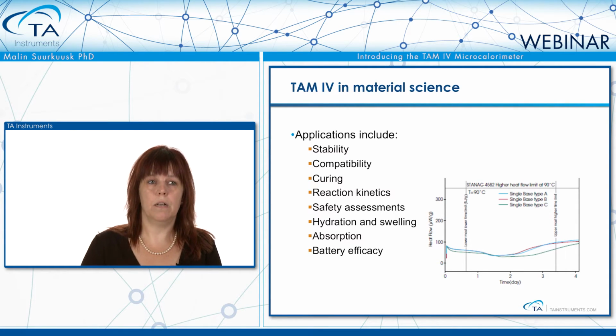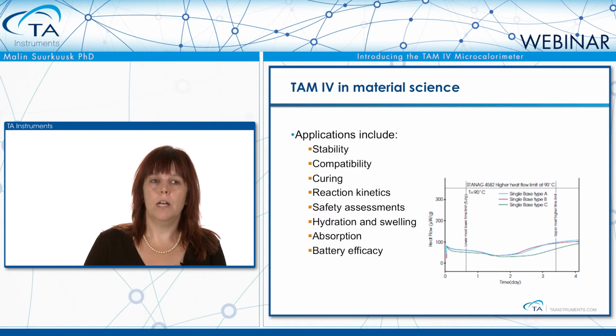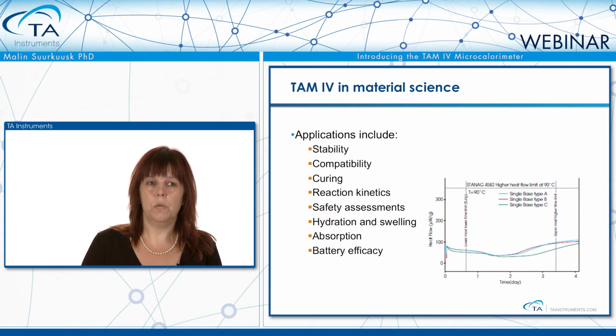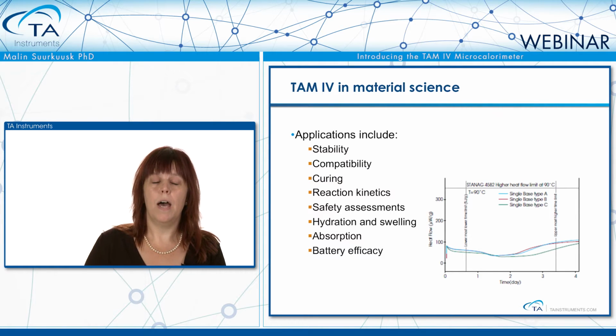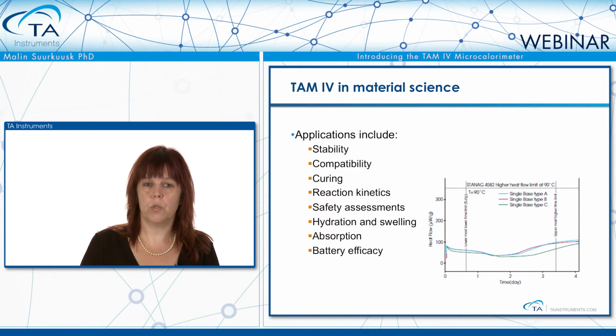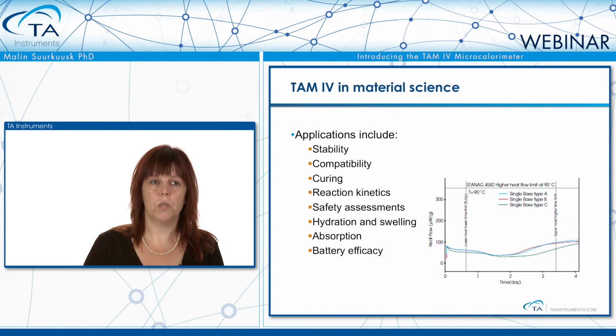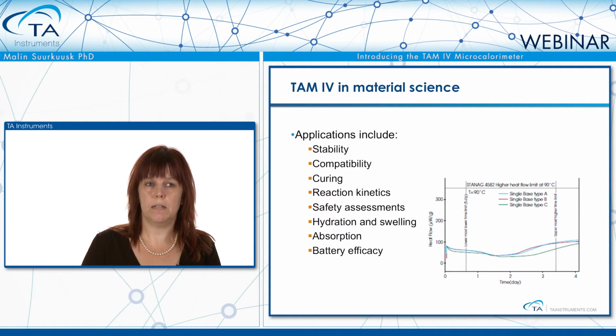In the example here, it's a measurement according to a Stanag method where safe storage of a propellant is tested. It needs to qualify if a propellant can be stored for up to 10 years. So what you do is you put your propellant into a closed ampule, put it into a temperature between 60 or 90 degrees as described by the method, and measure for the amount of days that's also described for that particular temperature. The square you see in the plot, that's where the heat flow of the sample must stay to be safe for these 10 years. It needs not to exceed the higher heat flow limit at that temperature.